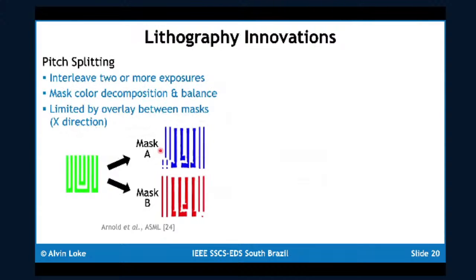So what are some of these innovations? The first notable one is pitch splitting. Here you have a very fine pitch you cannot print in one mask, and so you basically interleave 2 or more exposures that you can print with one mask each. This works, but has a fundamental limitation: there is misalignment or overlay tolerance between the masks that will limit, for instance in this case, how much you can push this technology.